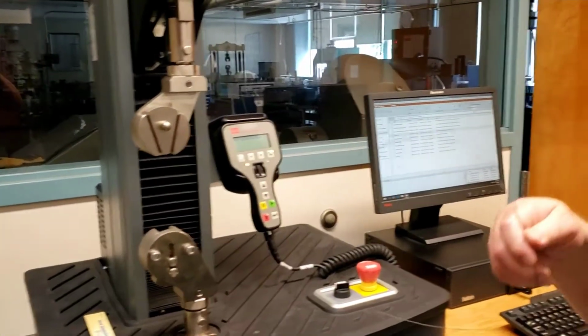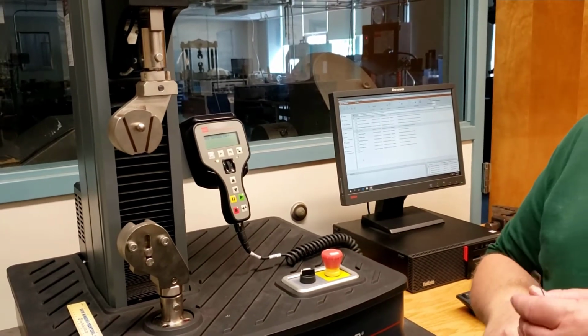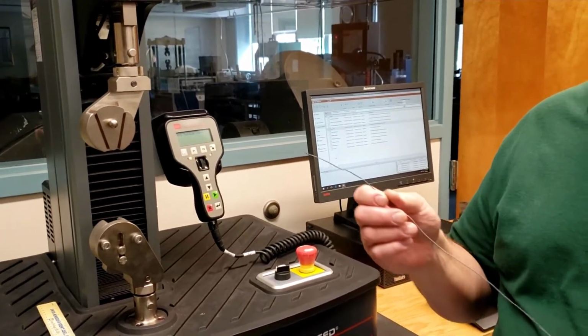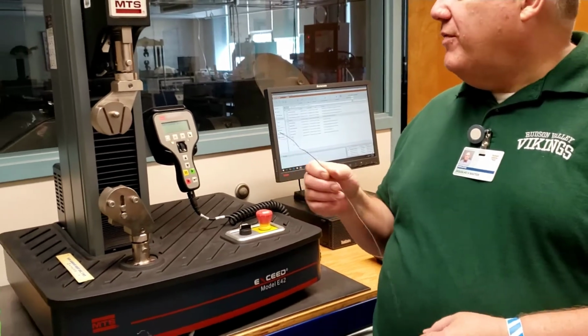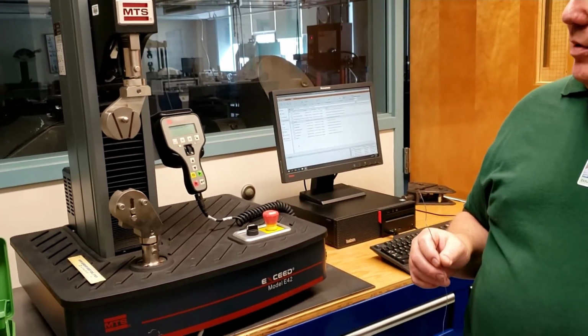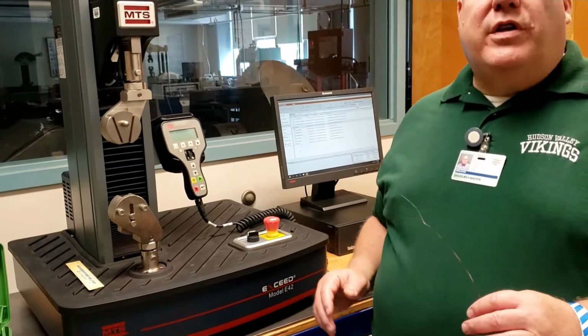And so what you're going to do is pull a 1 millimeter sample just off the wire spool. That's the one we're going to do now. And then you're going to do 0.9, 0.8, 0.7, 0.6, and if you can get to it, 0.5 diameters, and test them, and you will see the curve get taller and shorter as it goes. Then we're going to take those pulled samples, because we're going to cut enough to do 2 tests, and we're going to put the samples in the oven and heat them for about 15 minutes at 300 degrees Fahrenheit.